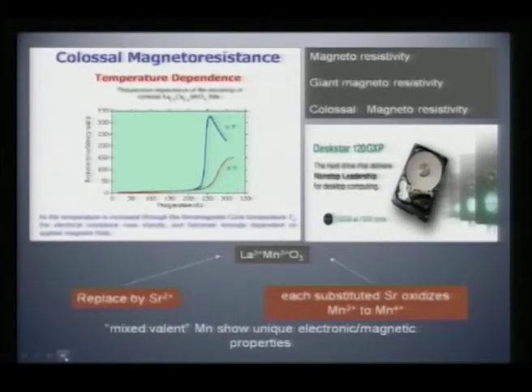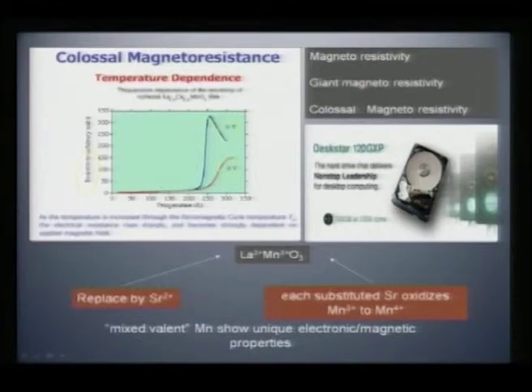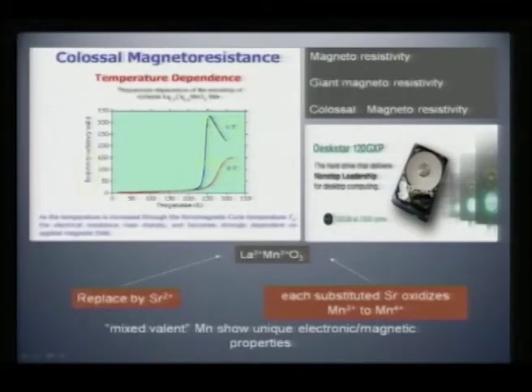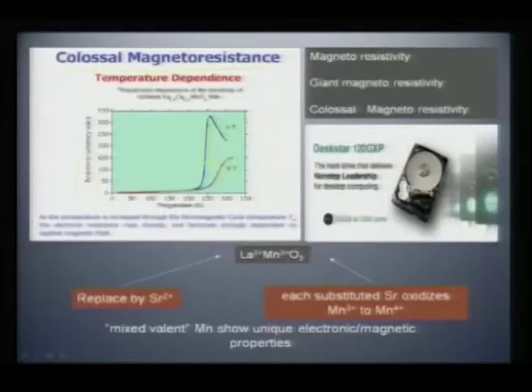So, what is this colossal magnetoresistance? This is a cartoon that clearly tells us that there is change in the resistance or change in resistivity when you apply magnetic field or when you have absence of field. At 0 Tesla, that is absence of magnetic field, this is the insulator to metal transition that you see here. But once you apply a very high field of the order of 6 Tesla, you see that the transition shifts to the right side to higher temperature, and also the resistivity falls down by orders, and this is the term which is used for colossal magnetoresistance, meaning there is a huge loss in resistance when you apply a magnetic field, which has never been observed or reported in any oxides thus far. So, as the temperature is increased through the ferromagnetic Curie temperature, the electrical resistance rises sharply and becomes strongly dependent on the applied magnetic field.